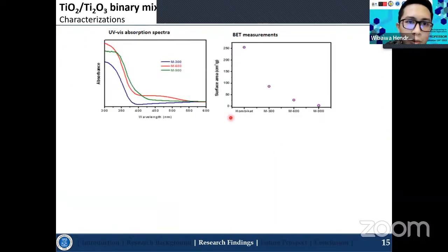And based on the UV-vis absorption spectra, we can also see that the M500, which is the yellowish titanium dioxide, absorbs in the visible light range, whereas the M300 is not active under visible light. And also from the BET measurements, the surface area gradually decreased with increasing calcination temperature, which is in agreement with the theoretical fundamental aspects.